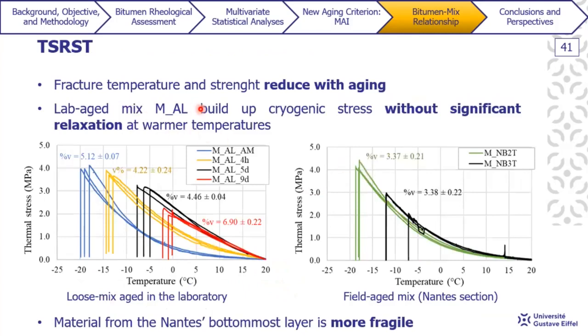So the thermal cracking propensity seems to increase with aging, as we observe a reduction of the fracture strength and temperature. And this is illustrated by this shift of this curve here toward the warmer temperature. This curve represents four aging levels of loose mix that were aged in the laboratory. This one here, the blue one, represents the bitumen after mixing. The yellow one represents after 4 hour aging. The black one represents after 5 day aging, and the red one after 9 days.